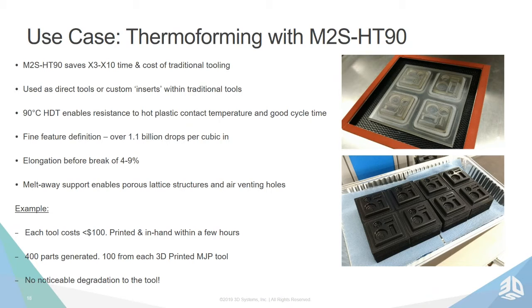And there was no noticeable degradation to the quality of those parts over the course of producing those 400 parts. The HT90's material elongation at break is between 4 and 9%, and that provides just enough flexibility to allow for the removal of those final formed parts from the dies without damaging the die or destroying the small features on the die surface. All in all, using the 3D printed tool and the HT90 material in this use case saves anywhere between 3 to 10 times the cost and time of traditional low volume tooling. So that's quite a significant time and cost saving.